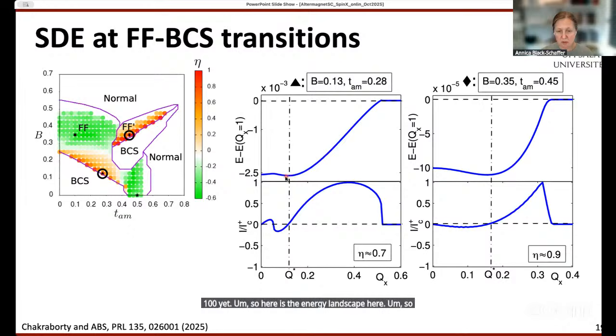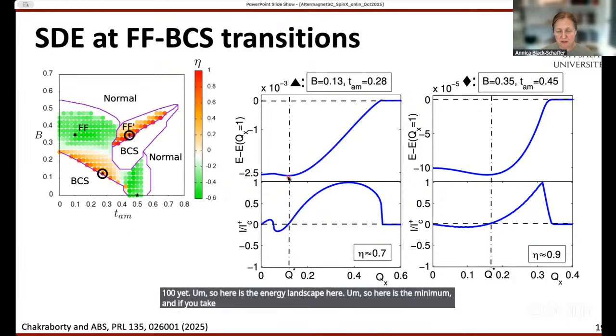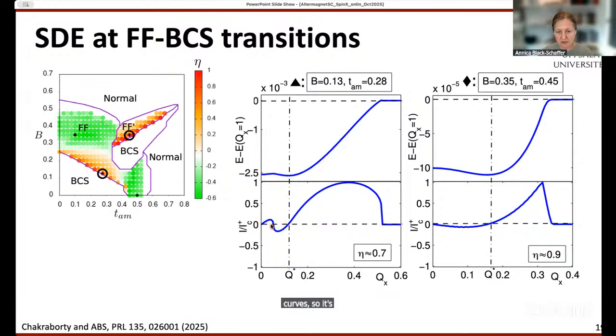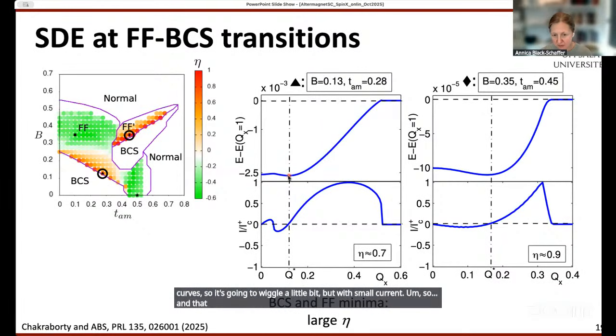Here is the minimum. And if you take the derivative of this, it's going to be reasonably high on this side, so higher current in the positive direction. On this side, it goes from a minimum to a maximum to a minimum, but it's rather small. So it's going to wiggle a little bit, but with small current. That is because both this FF state and the BCS state here at 0Q are minima. So it's going to be rather shallow, but the derivative still wiggles.